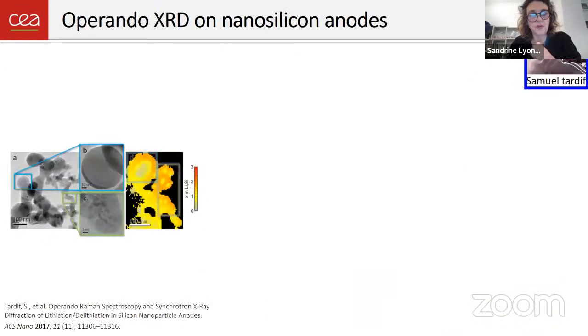So let me show a first example of one synchrotron investigation on a silicon material. That one is a pure silicon material where we had some nano-sized crystalline particles. And the question we had was to understand the lithiation mechanism. We know that lithium will come from outside and create a shell that will amorphize the material and then go down to the core. And at the end of the lithiation, you get amorphized silicon. The question for us was to understand the strain and stress that develop during this kind of process on the core. So this is a kind of standard XRD experiment.